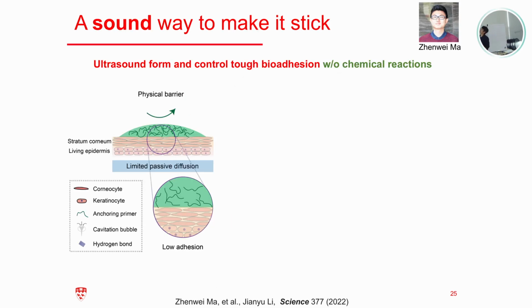And instead of using ultrasound for imaging or drug delivery, what we propose here is to use ultrasound to control the transport of this adhesive polymer through the tissue barrier. We call it a very sound way to make the hydrogel sticky. The beauty of this strategy is that the adhesive polymer can readily penetrate through the tissue barrier. We have no need for significant chemical reactions with the tissue. The benefit is reduced side effects and much higher controllability. I will show you in a few minutes.